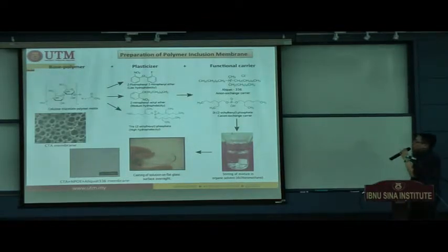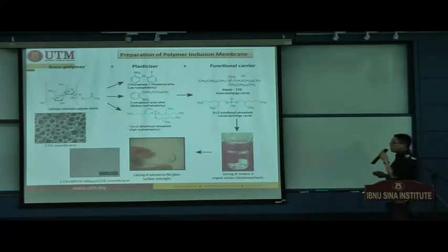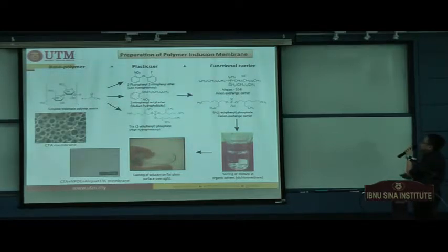We have cellulose triacetate as the polymer matrix, and we put in different kinds of plasticizer. You only use one type of plasticizer for each membrane, but you can select depending on different hydrophobicity. These plasticizers are famous plasticizers used when people are making ion selective electrodes for different kinds of ion sensors. And these are two types of functional carrier: an anion exchange carrier, Aliquat 336, and di(2-ethylhexyl) phosphate, which is a cation exchange carrier.